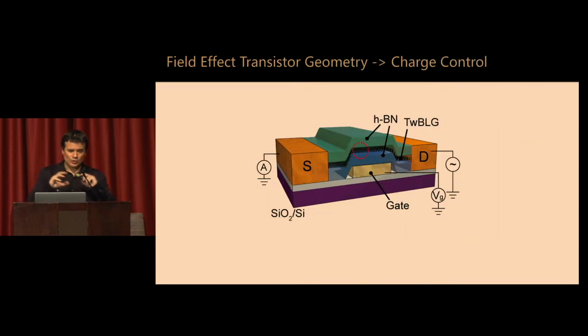All right, so then we continue doing nanofabrication of this, and we come up with a device which looks like this. It has our twisted bilayer graphene at the magic angle or at any angle that we choose. It has top and bottom hexagonal boron nitride, so that it makes a nice sandwich, protecting the graphene. And we contact the graphene with source and drain electrodes, so that we can apply a voltage and measure a current circulating through it. And we do all this in a field effect transistor geometry, for those of you who are engineers, or basically, we have an extra metallic plate. The graphene and this metallic plate form a parallel plate capacitor. So if I apply a voltage, I can change the density of carriers in the twisted bilayer graphene, okay?